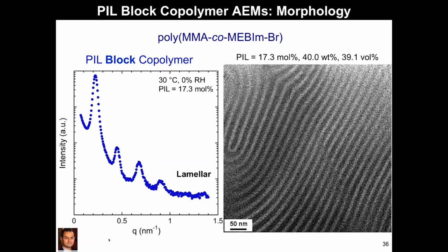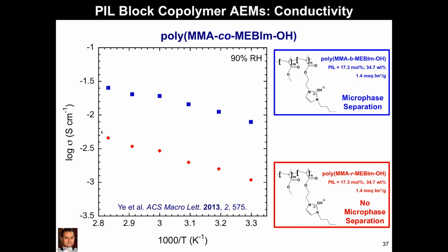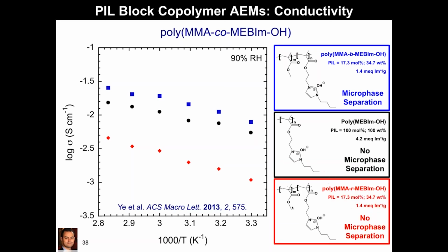So we have these conductive channels in the block copolymer. And as I expected, if you plot the conductivity versus inverse temperature at a high humidity for the block copolymer in blue and the random copolymer in red, you can see a significant difference in the conductivity, and that's due to that nanostructure. So all things being equal here, the only difference is the morphology type: same charge density, same water content, everything. Another interesting feature is that the block copolymer is actually a little higher at this specific condition than the homopolymer, even though the homopolymer had a 3 times higher charge density and more water. Morphology has a big impact on this.